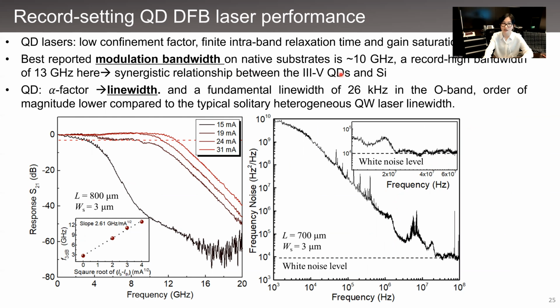But here we got a record high value of 13 gigahertz, and just with polished facets, and there is still a lot of room to improve the modulation performance. For example, adding anti-reflection facet coatings and depositing the metals on a thick dielectric for lower capacitance, etc.